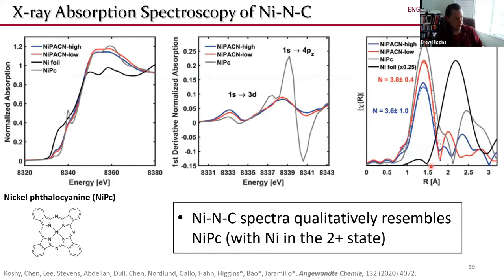David was very diligent, did a bunch of X-ray absorption spectroscopy measurements, and I realize this just looks like a bunch of squiggles on a slide, but ultimately the end result of these experiments was that these catalysts seem to have structures in them that looked somewhat along the lines of this nickel phthalocyanine molecule that I show down in the bottom left here, that had a nickel ion in the 2+ state coordinated with these pyrrolic nitrogens within this kind of graphitic looking macrostructure.